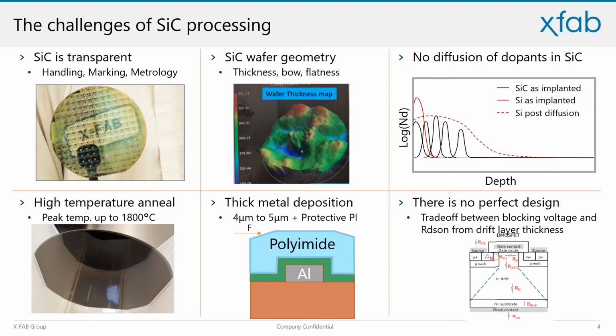The third challenge lies in the physical difference between the silicon carbide and silicon lattice. In silicon, you implant the dopant on the surface, and through diffusion, the doping layer is created. This will not work for silicon carbide. Here, practically no diffusion takes place. The dopants stay where they have been implanted. The only way to achieve selective doping is to use multiple implant steps to create a box profile, which creates a low throughput through the implanters.